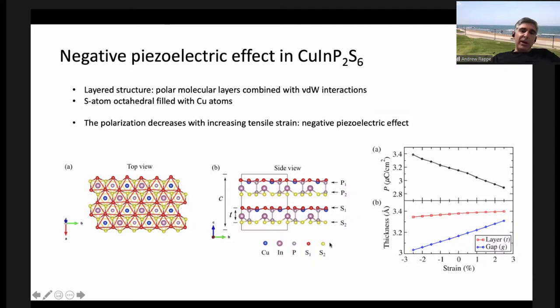Okay. So the interesting property of this is a two-dimensional material. It's a three-dimensional crystal, but you can see there's no bonding between one sandwich and the next. Each of them is chemically closed off. So when you compress the material, here, this is the ordinary lattice parameter. If you compress it, mostly the gap between layers compresses. The layers themselves hardly compress at all, okay? And what you can see is compressing it makes the polarization go up, or expanding the crystal makes the polarization go down. So we can computationally verify that this is a negative piezoelectric.